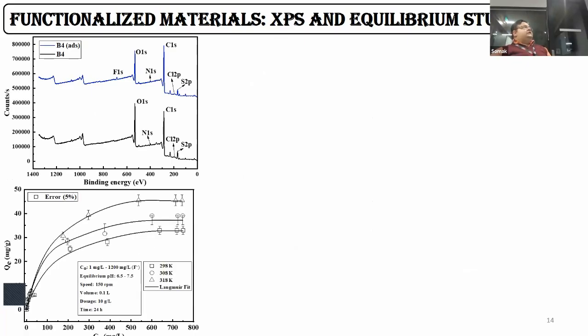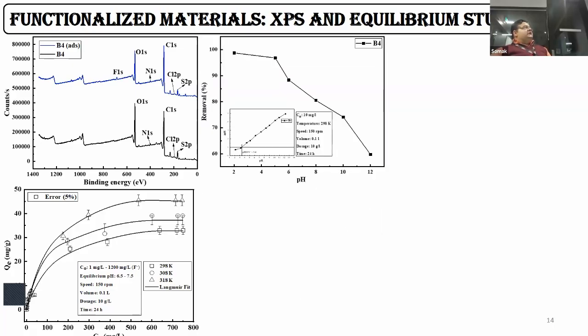Now why do we have to choose B4 beads? Because it gives a very high uptake capacity compared to others. The equilibrium uptake capacity is the highest for the B4 beads, around 25 to 30, and it starts increasing as we increase the temperature. The reason being fluoride ions show increasing mobility at higher temperature, making this an endothermic adsorption process.